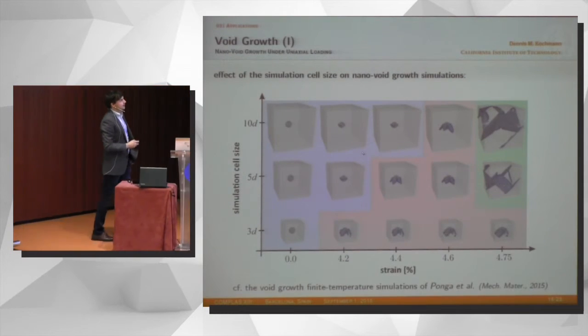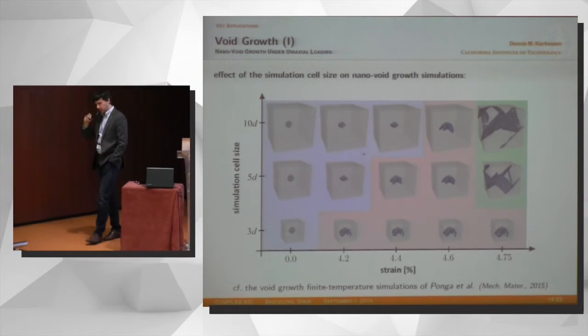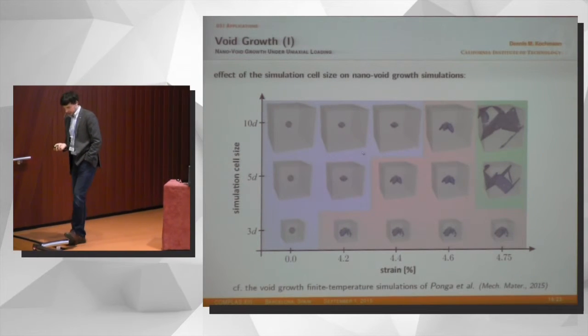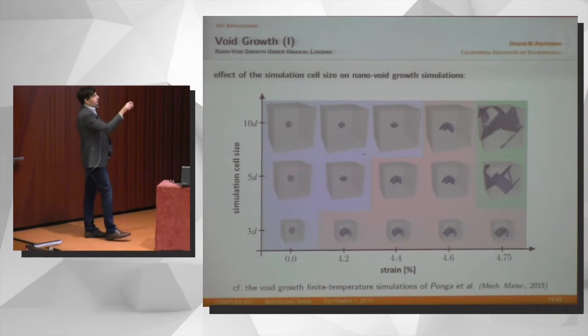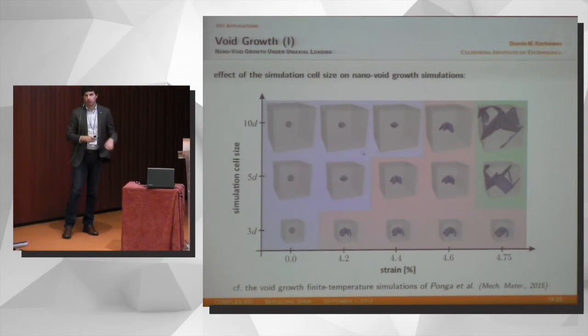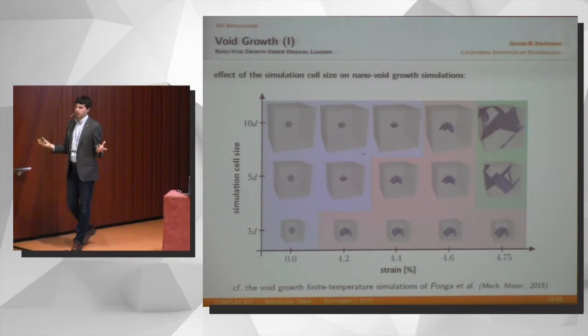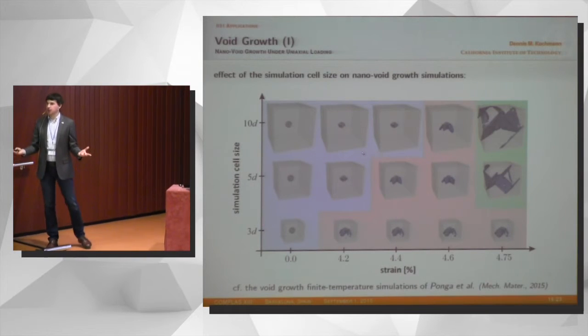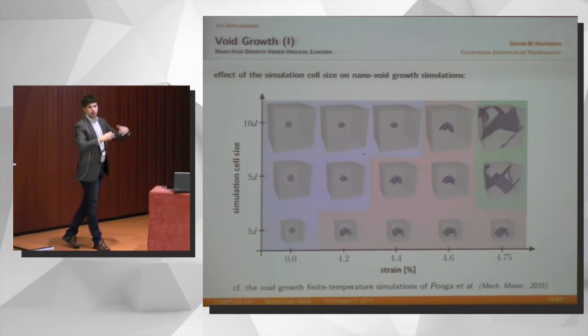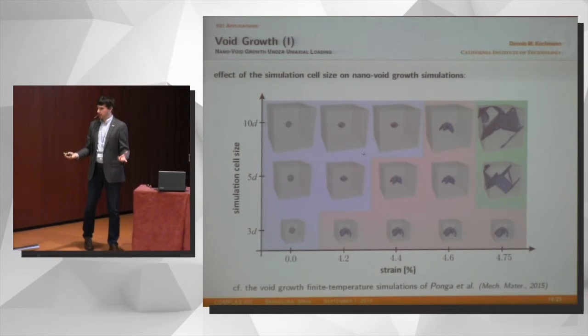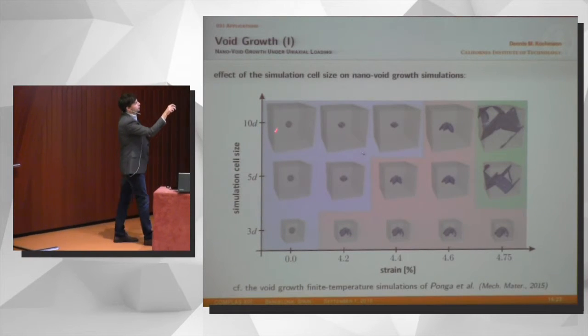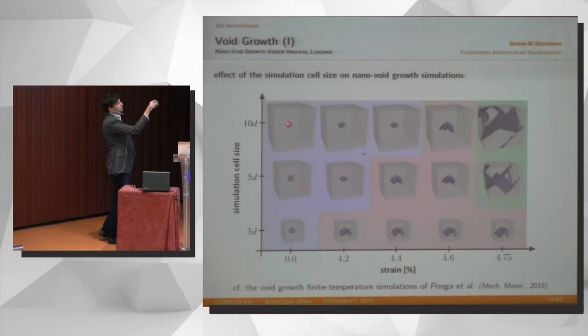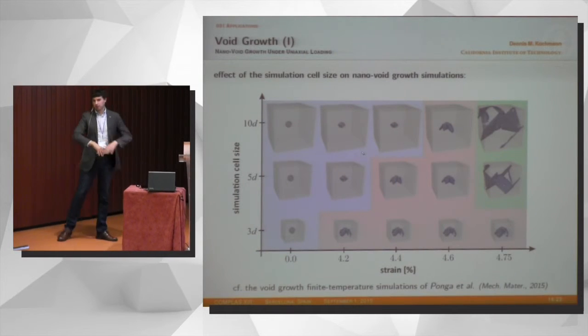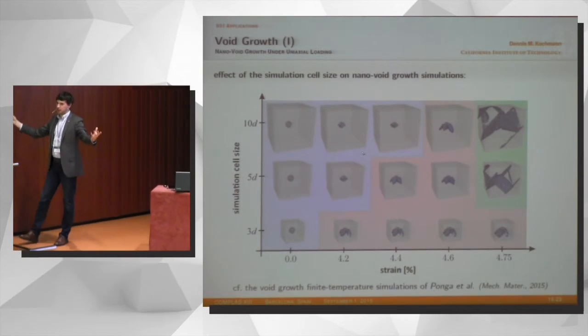So first, this is a very simple scenario, but I'd just like to illustrate one feature that we have to be very, very aware of, and that is, let's say you're interested in void growth or in general, defect nucleation around voids. And many of us are interested in this because this is the precursor to ductile failure. It's interesting for spall strength of metals and so forth. So what you normally do is you create a nanovoid. This is a few nanometers in size. You put it in a box, and you pull on it, or you hydrostatically expand it.